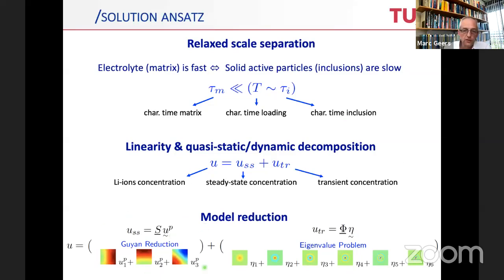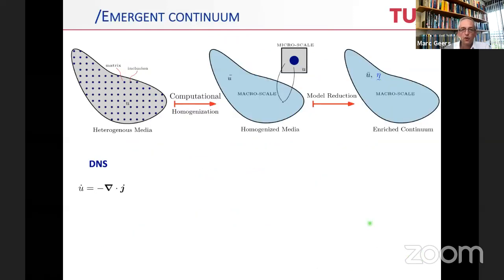So the steady state contribution can again be obtained by reducing it by static condensation, the Guyan reduction, whereas the transient contribution can again be determined by different modes, in this case diffusional modes, times their amplitudes eta. So again, the additional degrees of freedom have a clear physical meaning. If you now look at the problem, the heterogeneous medium is on the left, and computational homogenization gives you something that is homogeneous, but is still connected to the microscale at every moment. Whereas pushing it further, you end up with an enriched continuum in which the coupling with the microscale is gone, but in which new additional degrees of freedom, the etas, emerge.